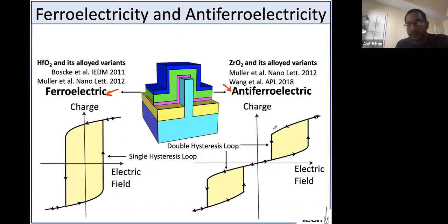Without going into the physics of it, what it essentially means is that if you look at the hysteresis loop, there will be two hysteresis loops in the polarization versus electric field characteristics. Each of these transitions here represents a phase transition, while in a ferroelectric, these are not phase transitions, these are just rotation of the polarization vector.